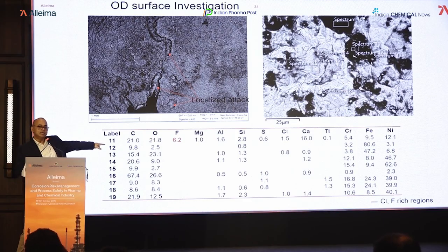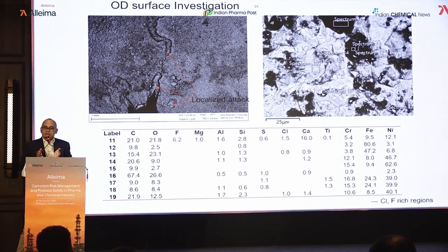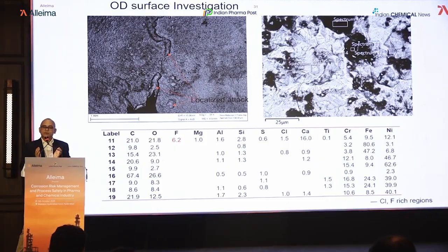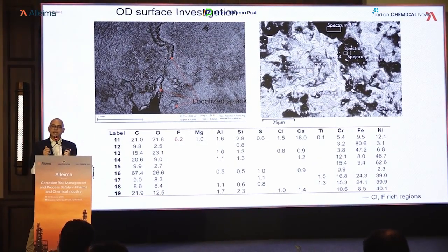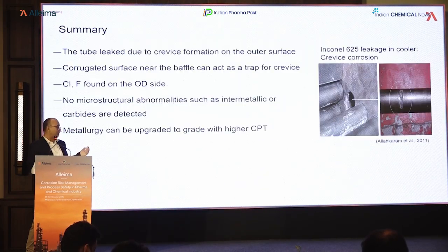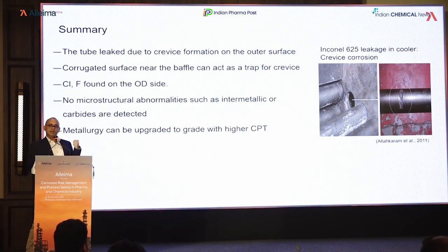You had chloride, and you may have initially wear, and then that gives you some narrow region where you have aggressive media, and that is called basically the crevice corrosion. So probably this was the crevice corrosion. There are articles in the literature. They have also seen the similar crevice corrosion when they have used alloy 625. Yes, we can again improve the metallurgy, or we can look into the design. So how we can stop that.